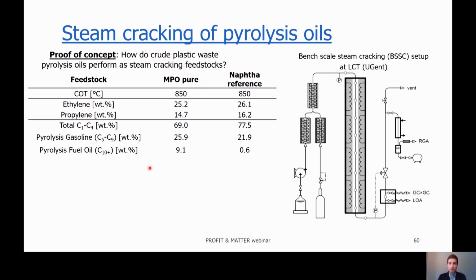As I said in the beginning, we performed steam cracking experiments of pyrolysis oils to assess the potential of the crude oils as steam cracking feedstock, basically as a proof of concept. We used a setup like this one, a bench scale steam cracking setup at the LCT in Ghent. We cracked an MPO pure with a coil outlet temperature of 850 degrees C, and used the same conditions to crack a naphtha reference feedstock, a fossil naphtha used in industry.